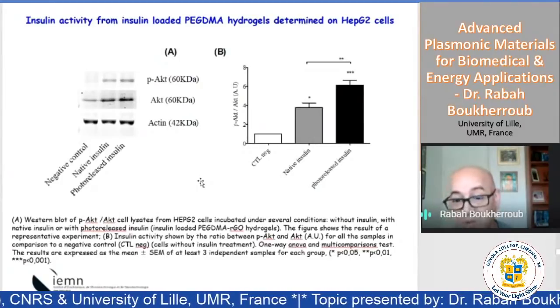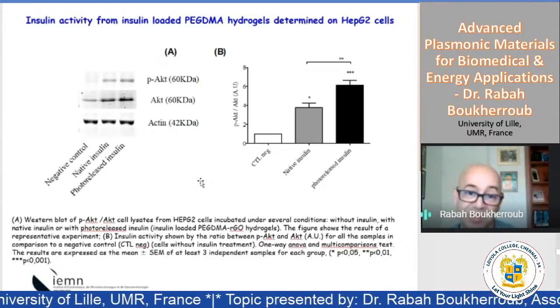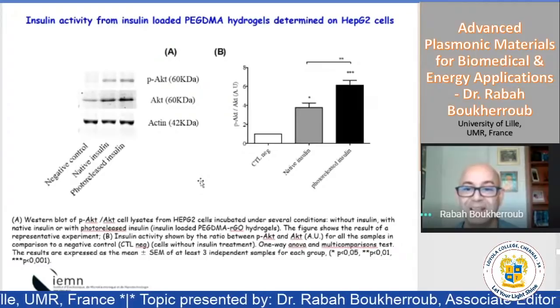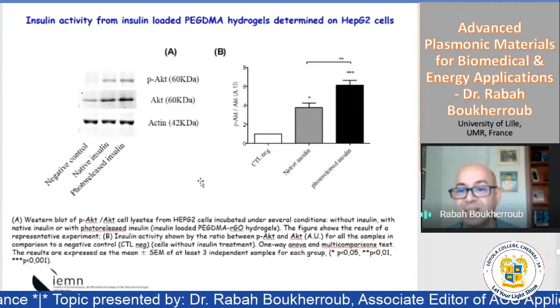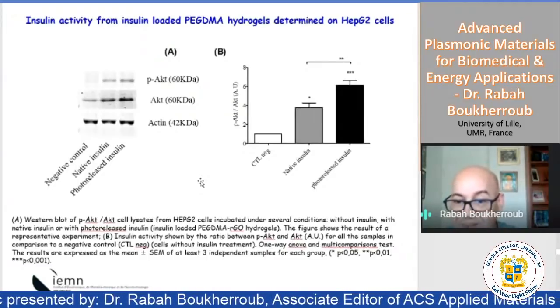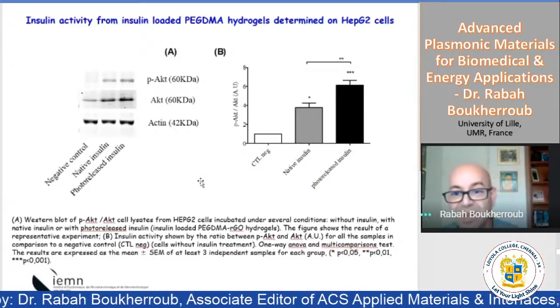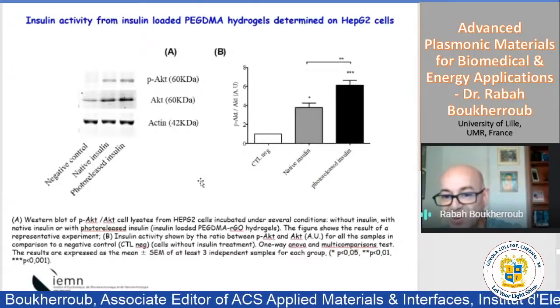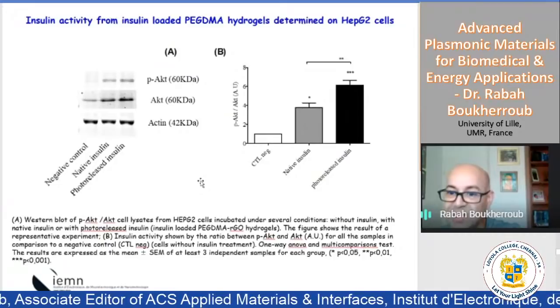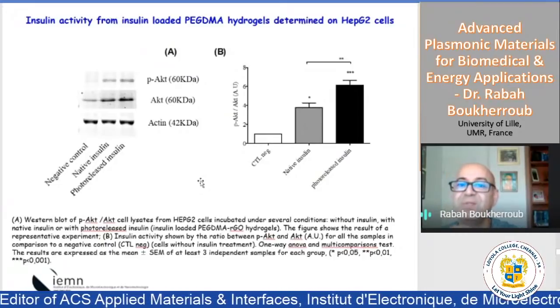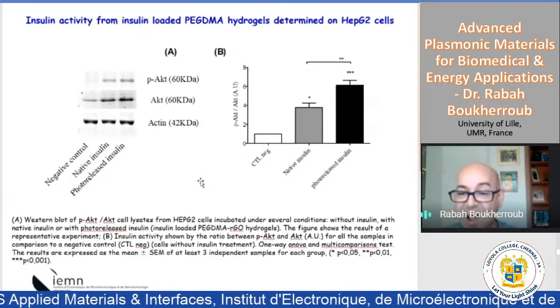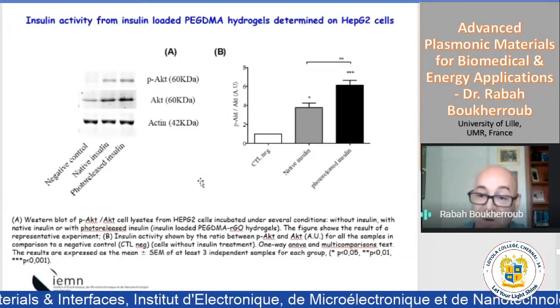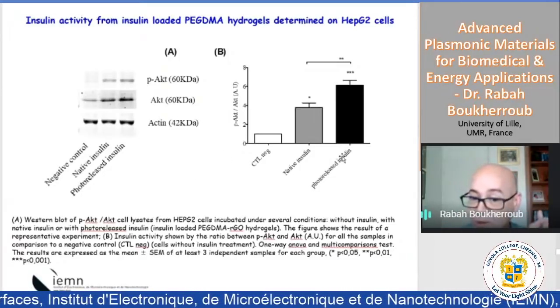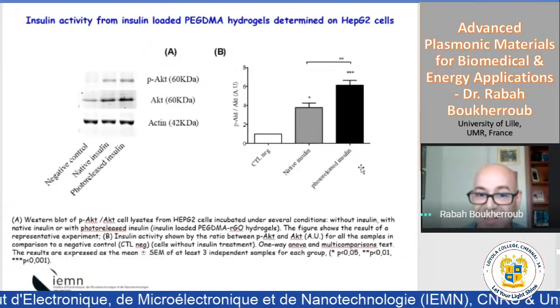Another point which is really critical: imagine now that insulin has an activity, and when it's loaded and released it doesn't have any more activity. You lose the activity. Then, of course, you can do nothing with this. Again, we're fortunate: when you compare the native insulin and the photoreleased insulin, the photoreleased has even much higher activity. We don't really know why, but it's definitely reproducible. It's not 10, it's not 20, it's more than that.